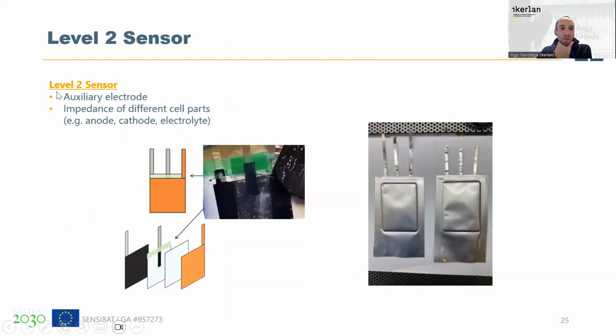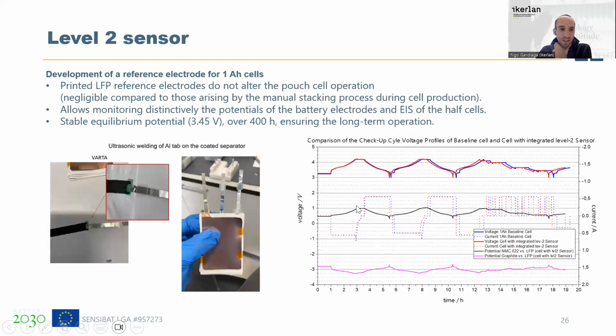And about the level 2 sensor, here we developed, as I said before, an auxiliary electrode. We place it on the separator of the cell, and in this case we have 2 separators. On one of them we have this auxiliary electrode, which is based on a printed LFP. Okay, so those are the cells. So we have a printed LFP reference electrode to measure separately the potential of, in this case, the NMC and the graphite,